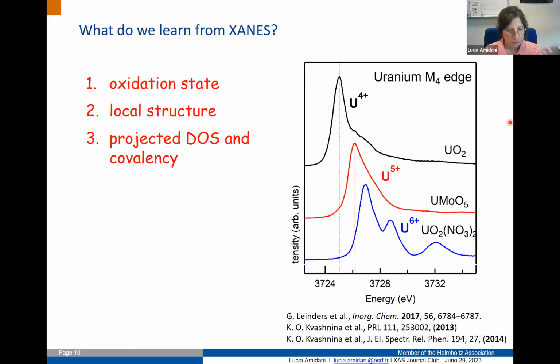And what do we want to learn? Everything that XAS is sensitive to. Maybe the most known property is sensitivity to the oxidation state, which is particularly pronounced for the M edges in general. Here I'm showing the M4 edge for uranium 4, 5, and 6 plus. The main absorption edge really shifts, and it is measurable—we can even quantify that.